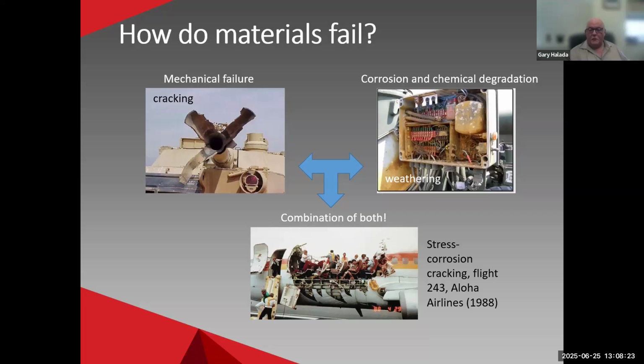And there's a lot of threat multipliers that make these things more likely to happen. For example, very high temperatures, very low temperatures, and sometimes the most dangerous of all is a combination of mechanical failure and weathering or corrosion. An example you see at the bottom of the screen there is a stress corrosion cracking caused failure. This was Flight 243 of Aloha Airlines in 1988 in Hawaii. And yes, that very much looks like a jumbo jet that turned into a convertible.